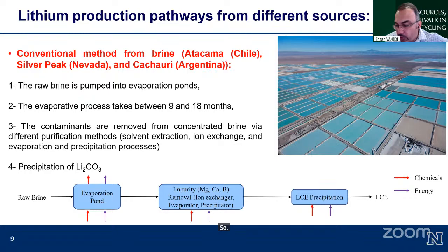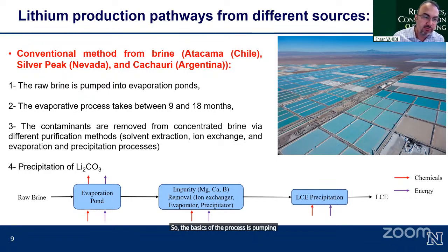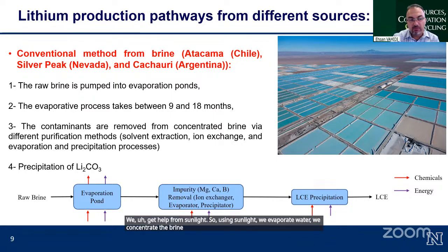So the basics of the process is pumping brine from underground, pump them into the evaporation ponds. It takes around 9 to 18 months for evaporation. So as you can expect, there will be no energy consumption for concentration. We get help from sunlight. So using sunlight, we evaporate water, we concentrate the brine, and then after some impurity removal stages, using a soda ash again, we can precipitate lithium as lithium carbonate equivalent.